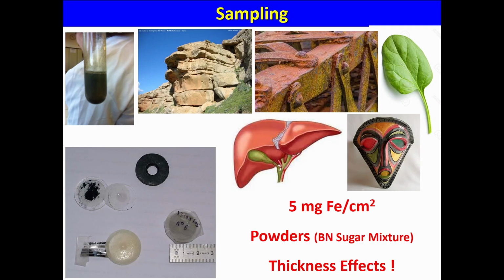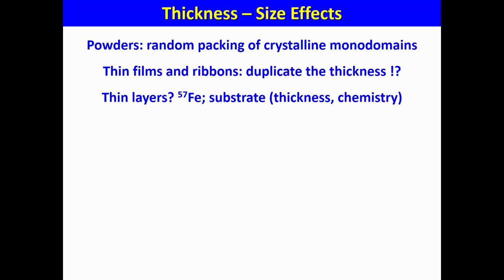And once I had a few milligrams of powder, I made a hole with a very small tip, maybe with a diameter of less than 1 millimeter, and I was successful in one day to get a good spectrum. So it's very important, because if you put your sample like this, you may need one month to get good statistics because the background will be very high. So it's better to spend time to prepare the sample before, to optimize it, and after you will have time. On the contrary, you will lose time.